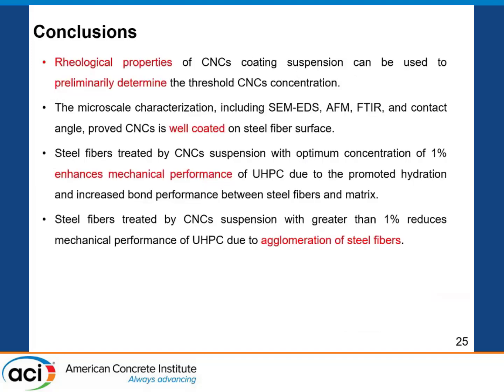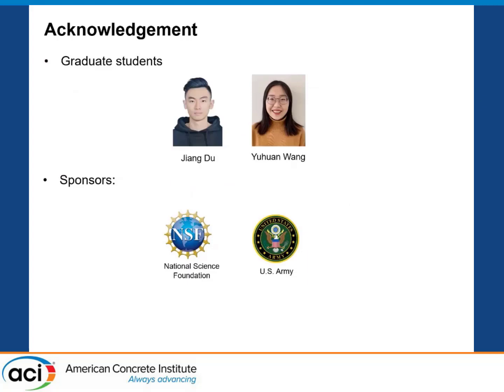So in conclusion, we can use CNC, an environmentally friendly and cost-effective material, to coat the steel fibers to enhance the bond between the steel fibers and matrix and improve the flexural properties. And we can use the rheology test to preliminarily determine the threshold concentration of the CNC content. For 1%, it performs very well, but beyond that, we have a problem with the bonding or the agglomeration of steel fibers, and research still needs to be done here. I will welcome any suggestions and comments on this subject.